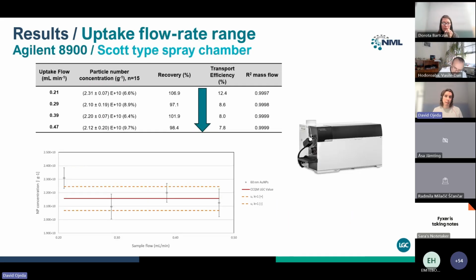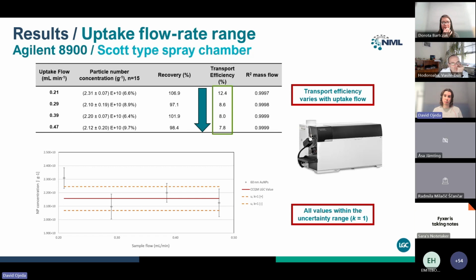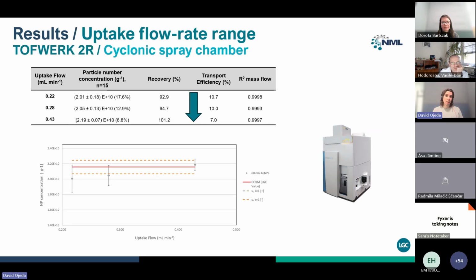Regarding the uptake flow rate range for the Agilent 8900 with the Scott type spray chamber, of course we can see that the transport efficiency varies with the uptake flow, but in all the ranges studied, we were still obtaining an accurate number concentration determination. And similar results were observed for the TOFWERK instrumentation using a cyclonic spray chamber.